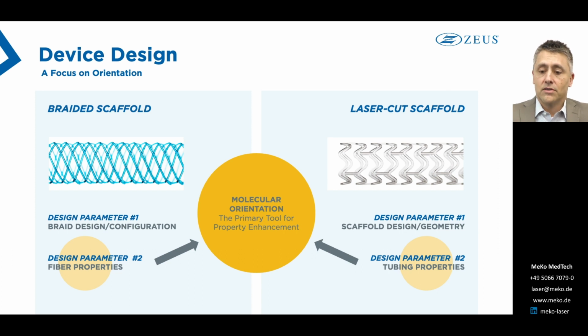So what we find is that the molecular orientation within the components is our biggest lever that we can pull to really enhance the component properties. And then those component properties really feed into the device design, and that's often through an iterative approach, aided by modeling, like finite element analysis. So in the case of a braided scaffold, it's the molecular orientation within the fiber, and in the case of a laser cut scaffold, it's the molecular orientation within the tube that's paramount.